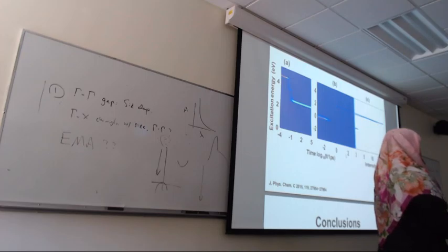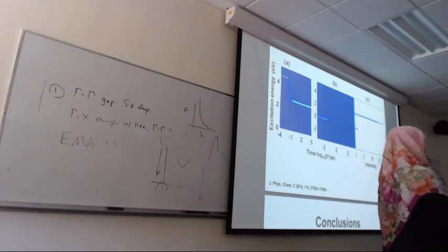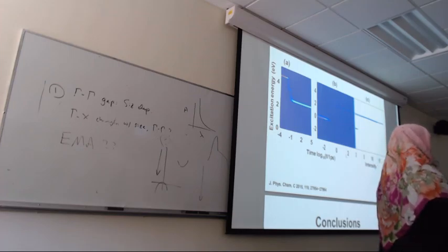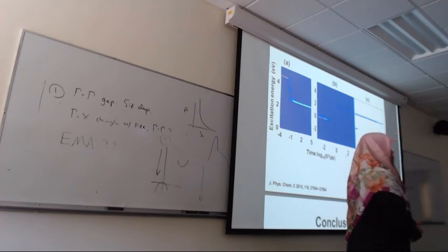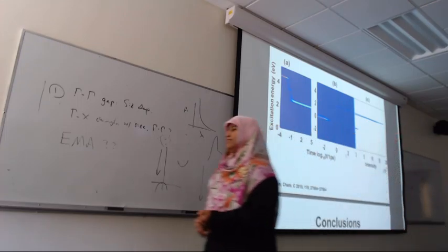Yep. EMA, the original, it's got about 1,000 citations from '95, so it was the very first one. And everybody since then has completely bastardized it because it didn't agree with their results. So they replaced terms in it with effective mass, dielectric constant, and then they basically treat those as adjustable parameters.